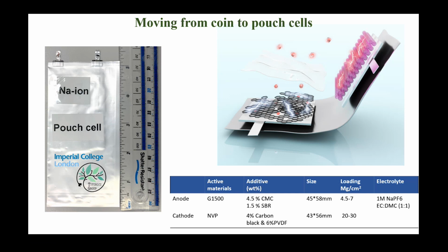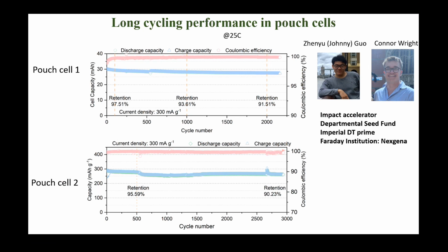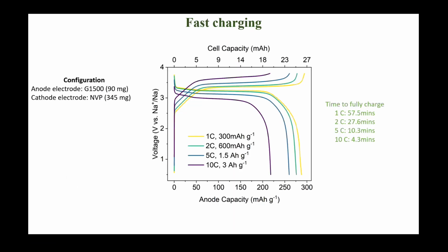So this is now something that we are trying to take to the next level, and we are making cells with commercially available cathodes from the literature, and we have very impressive performance for our hard carbons, where we managed to cycle them for 3,000 cycles, and we still retain a capacity of 300 milliamp hour per gram in a full pouch single layer cell. And the nice thing is that we can fast charge these carbon materials as well. So you see that in only 4.3 minutes we can still reach above 200 milliamp hour per gram.